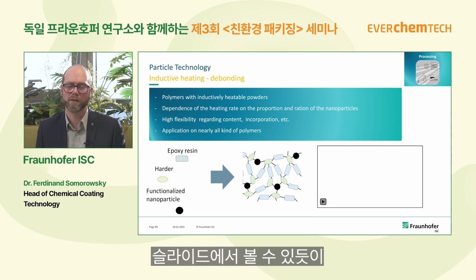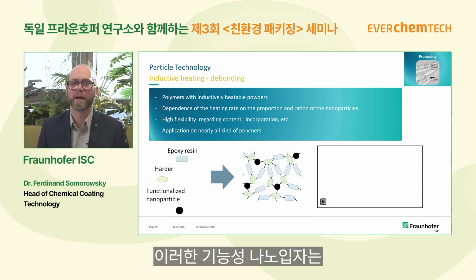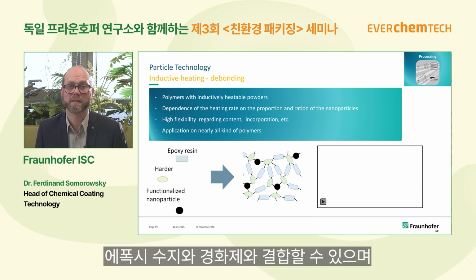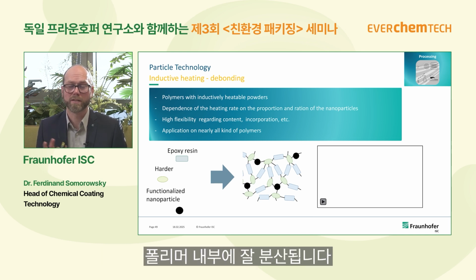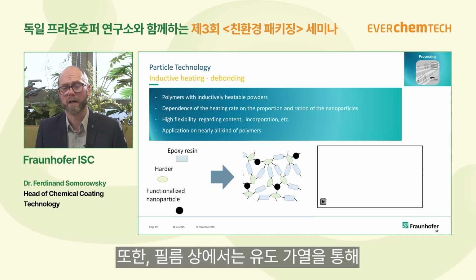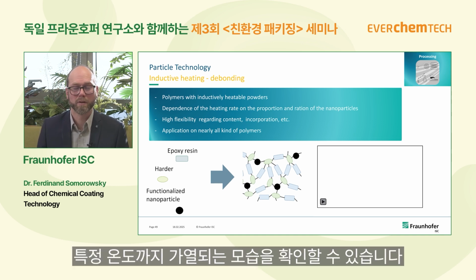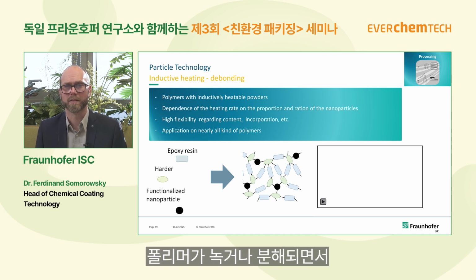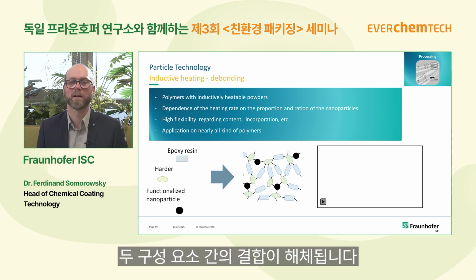It's shown here on this slide that you can combine these functional nanoparticles with epoxy resin and a hardener, and they are well dispersed in this polymer. On the film you can see that it's heated up to a certain temperature by the induction, and then the polymer melts or degrades, and this helps to release the bonding between the two components.